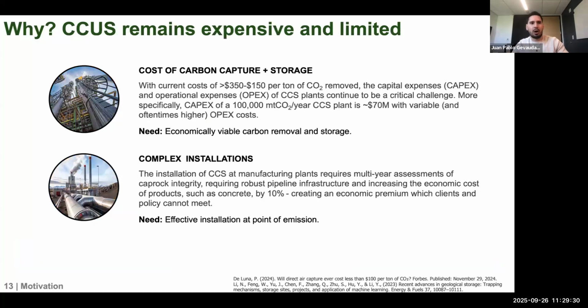All right, when we look at the other side, carbon capture, utilization, and storage, one thing that we need to keep in mind is that the cost of CO2 removal is actually really high. It's around $150 to even $350 per ton of CO2 removed. And that, of course, is because these are complex plants that require high capital expenses and high operational expenses to keep this carbon capture and storage going. Another component of this is that the installation of this technology is quite complex. We need multi-year assessments of the cap rock integrity, the geology. We need pipelines to pipe CO2. And oftentimes where the emission happens, where that cement plant is, may not be near a basalt cap rock that can actually take and store that CO2.